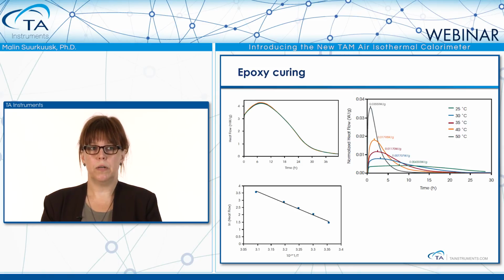Epoxy curing is another example. Epoxy curing is a quite energetic process. You don't need very much epoxy to go into the system to be able to study it. In the first upper left graph, there is 4 samples run at the same time, so the reproducibility of these kind of measurements is high. This data has been done at different temperature, which you can see to the right graph, where they have been done with 5 degrees differences during the measurement.